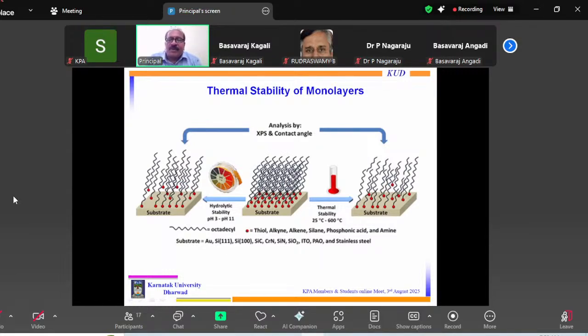Another group also demonstrated the stability of various monolayers. It is a cartoon of that. What you have is a substrate. You create monolayers of various kinds, which are written here. I will not go into them. Not only for silicon, they have done it for gold, silicon carbide, chromium nitride, silicon nitride, silicon oxide, indium tin oxide, and many more materials.